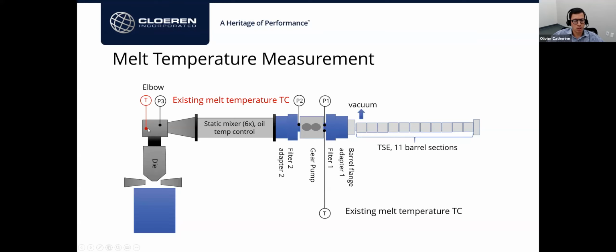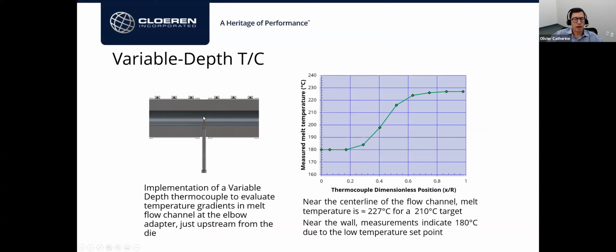There was a port we could use, and we used a variable depth thermocouple. This device is very useful for extrusion troubleshooting. We can measure the melt temperature at different locations, and we can plot this profile, from the wall of the melt pipe or the adapter all the way to the center of the flow. Once we're done with the measurement, we strongly recommend retracting the probe. Otherwise, it can get broken during startups or shutdowns or wrong manipulation.